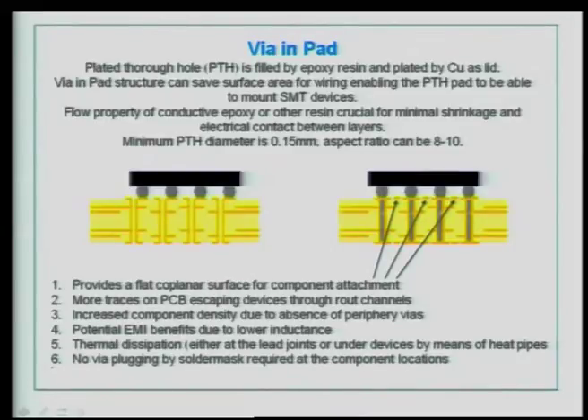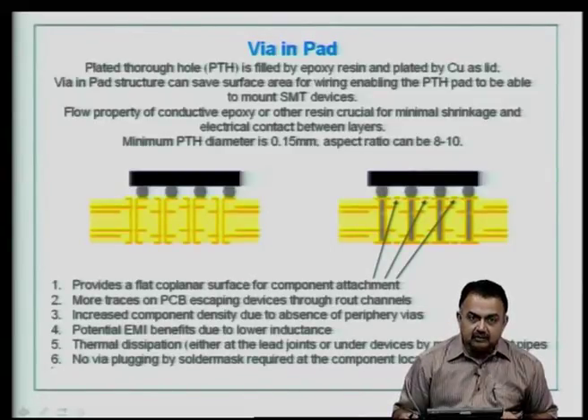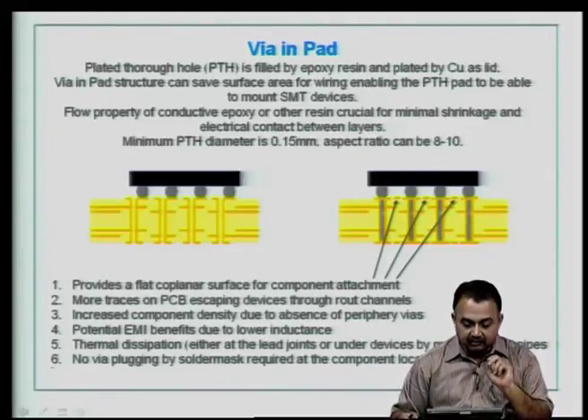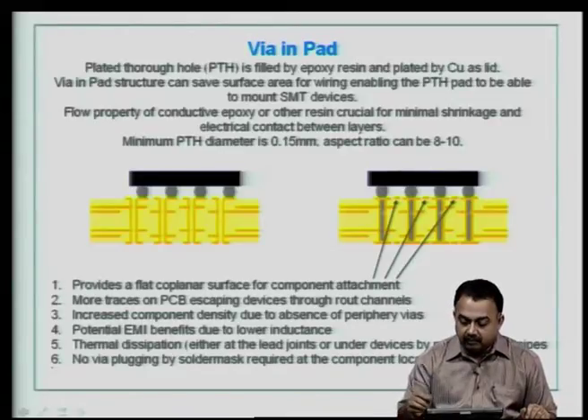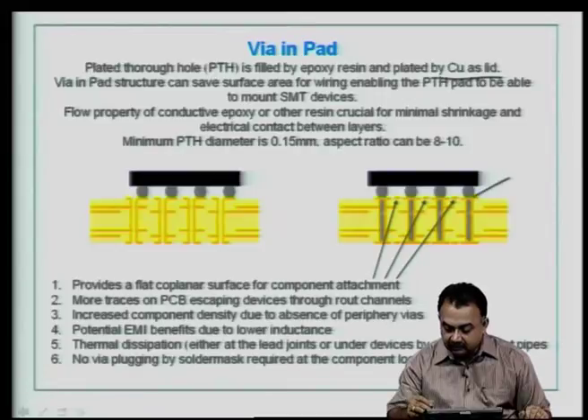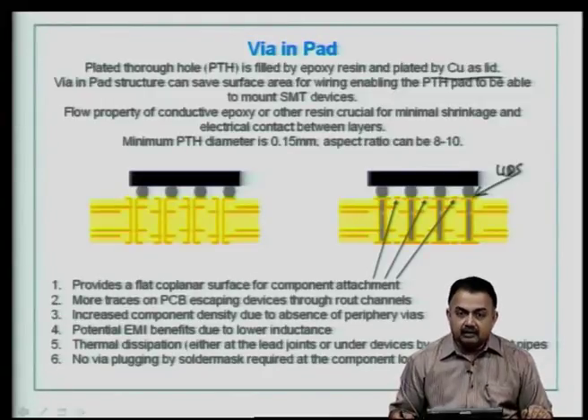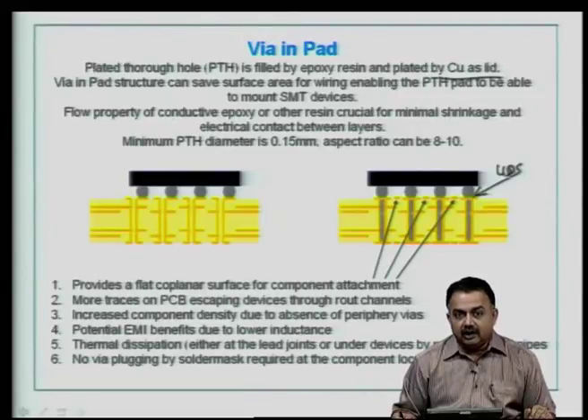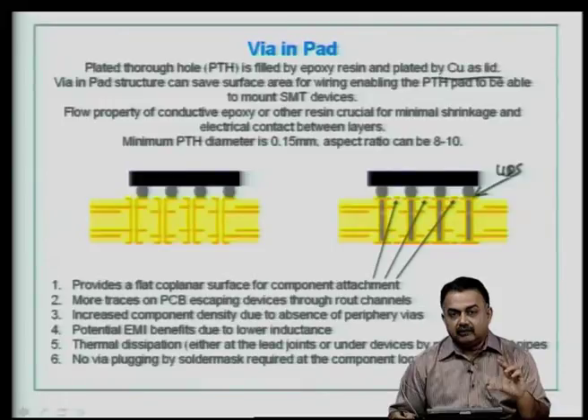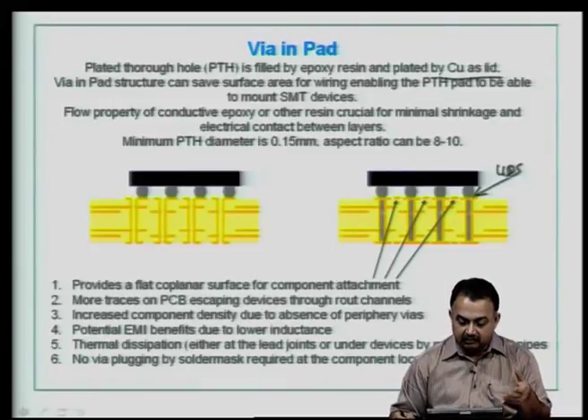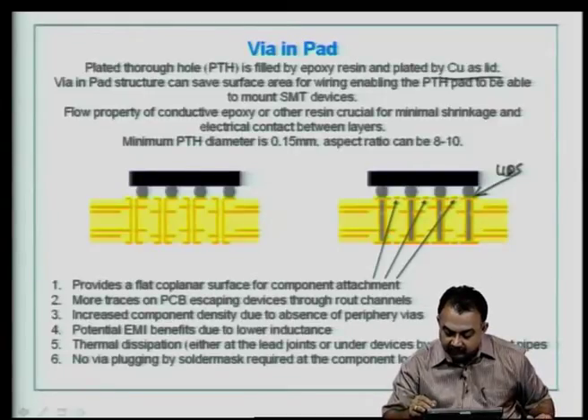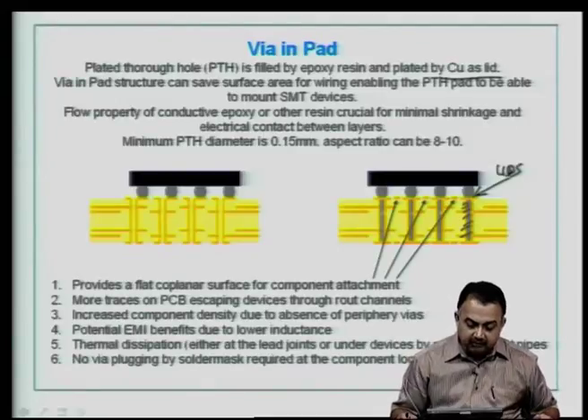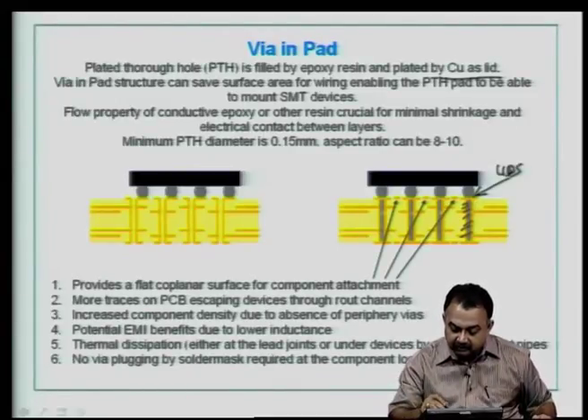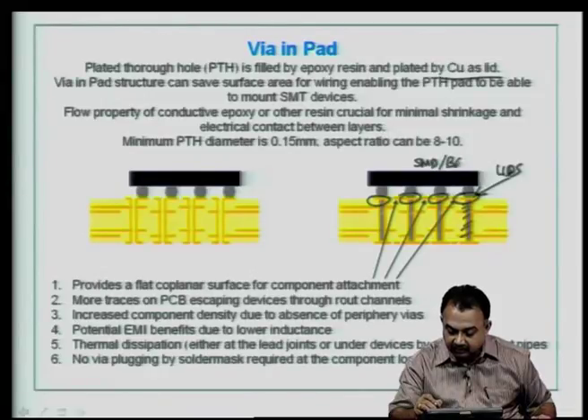The other one we have seen briefly is called a Via in Pad structure, a plated through hole. In this case a microvia made by mechanical drilling is filled by epoxy resin and plated by copper to form a lid. So, you can see here these are the lids where a through hole has been plated, and then they have been filled by the conductive material. And if you are talking about very large depth, then the conductive paste material has to flow much better rather than being a thick paste, because you want to cover the entire area of the through hole. Now, it is called Via in Pad structure because you can utilize the lid of your through hole for mounting your SMD or a BGA, let us say, or a CSP.